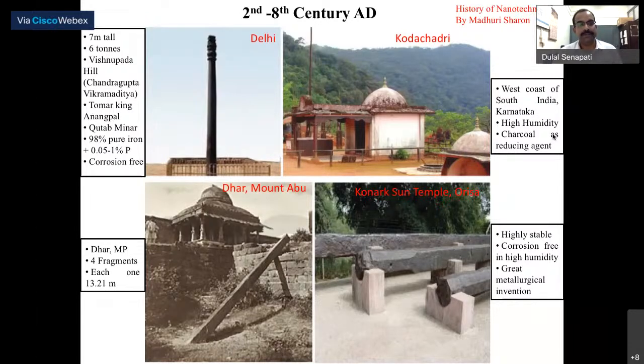Okay. And that was the Tomar king Anangapal who brought it from MP and then put it in Delhi. And later it was transferred to in front of the Qutub Minar. So that was pure iron of 98%, but it was mixed with about 0.05% to 1% phosphorus. And it was so nice that it's not being corroded.